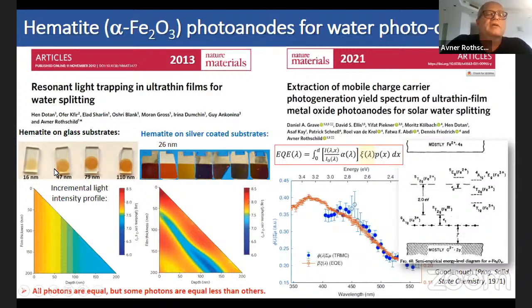And the way to enhance the light absorption is by making a resonant device. So instead of putting them on a transparent substrate, we put them on a back reflector made of a silver-coated substrate. And then, by resonance effect, in the case of silver, you can concentrate the light very close to the surface, within 10 or 20 nanometers from the surface. And by that, you can absorb a lot of light and minimize the recombination.